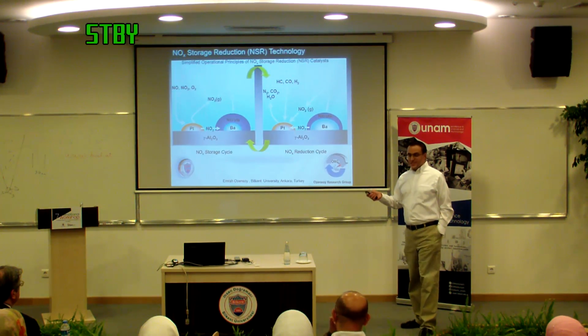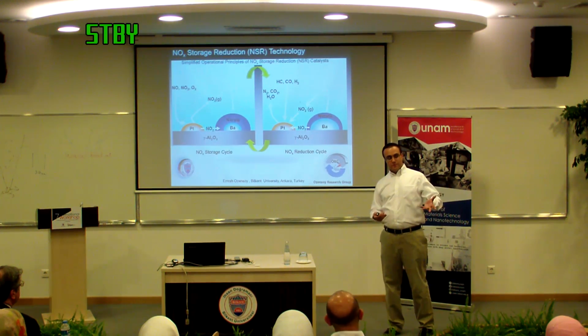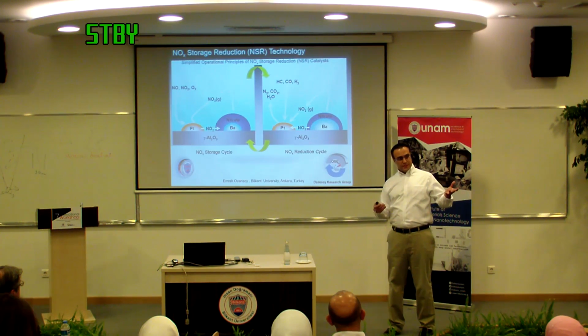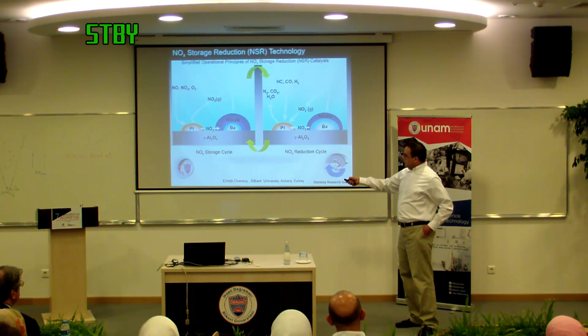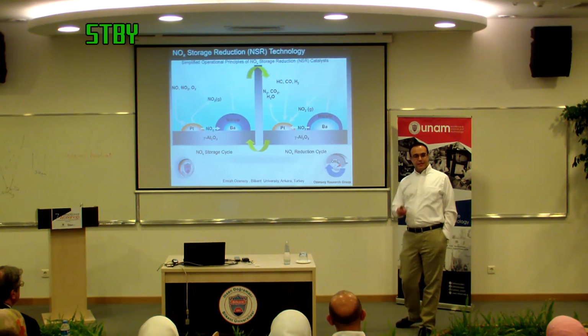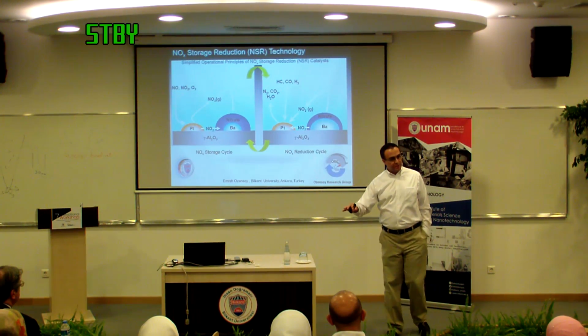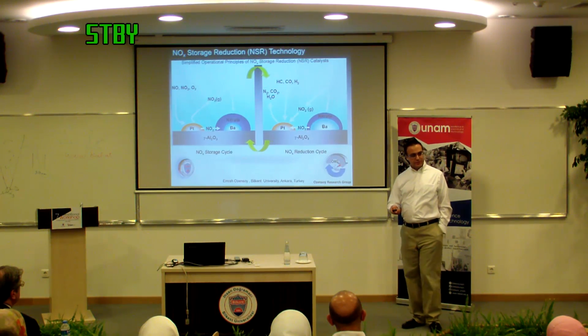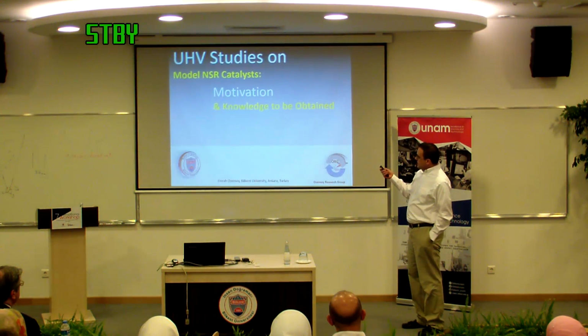One of the problems is, for instance, sulfur poisoning. Fuel has sulfur compounds, thiophene, and a lot of different things. And they stick to these active sites, metals, in the form of sulfides and sulfates like hell, and they kill your active site very quickly. So you find out ways of sulfur tolerance. So those are some of the things that we have been doing.